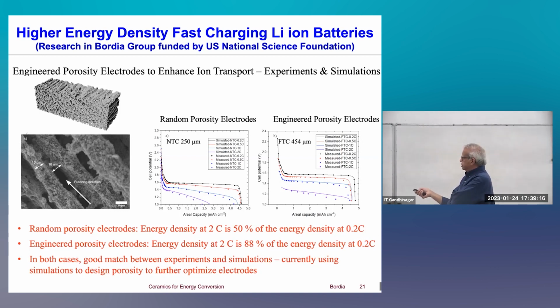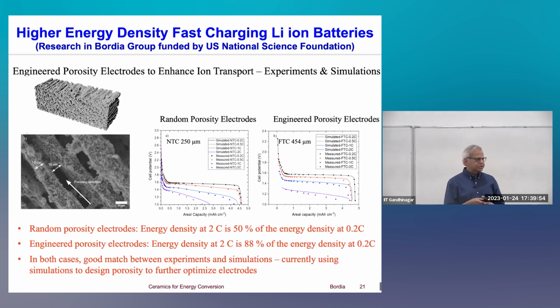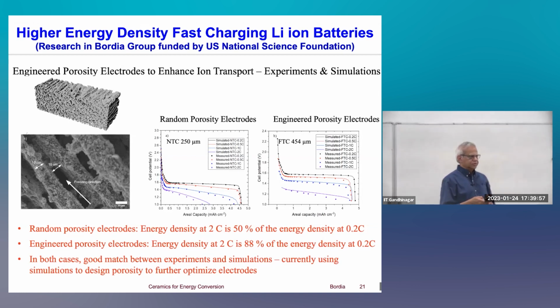Just to show you some data on this: with regular porous electrodes, when we charge at a fast rate, the capacity drops by about a factor of 2. With these engineered porosity electrodes, even at the fastest rate, the capacity drop is only about 5%. So that's a significant improvement in the retention of capacity at fast charge-discharge rates. We're continuing to work on it, and there's a lot of potential to further improve it. Now we are using simulations to design the optimal microstructures and then ways to make those microstructures. So it's an ongoing project.